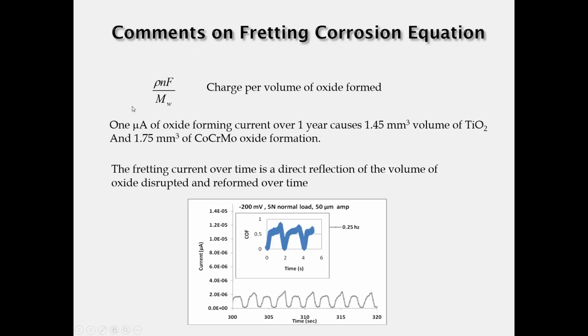So just to emphasize, the charge per cation, or charge per unit volume, is important, and you can use this term to make estimates of how much volume of material would be lost from a metal surface or how much oxide is formed. So 1 microamp over 1 year will give you about 1.5 millimeters cubed of TiO2 and about 1.75 millimeters cubed of cobalt chrome oxide.